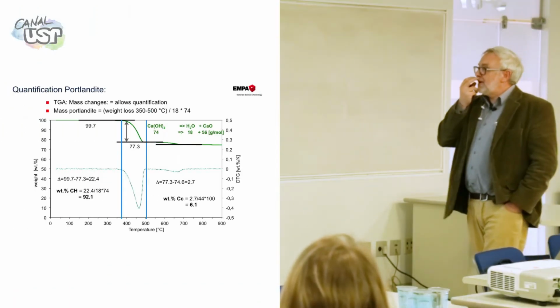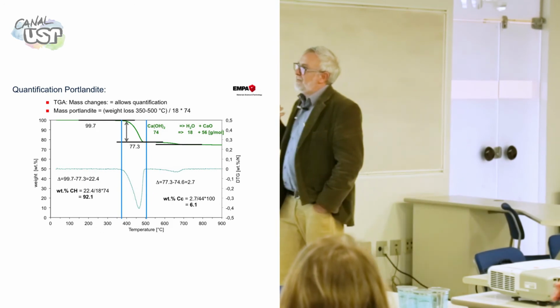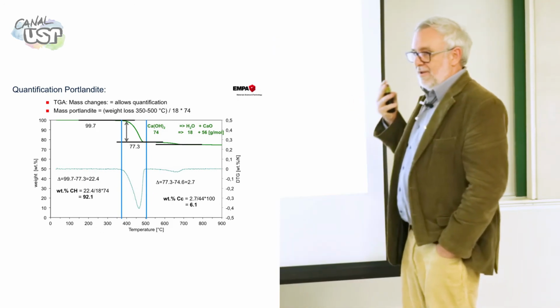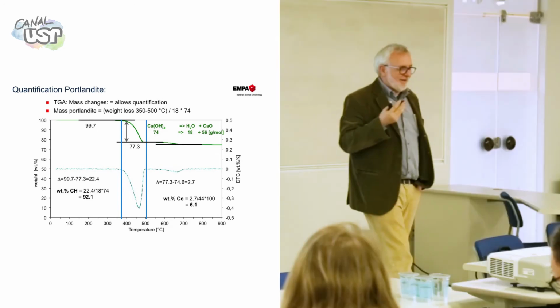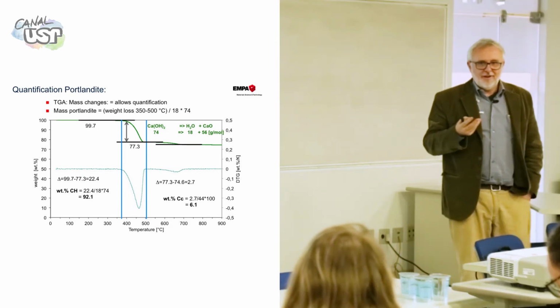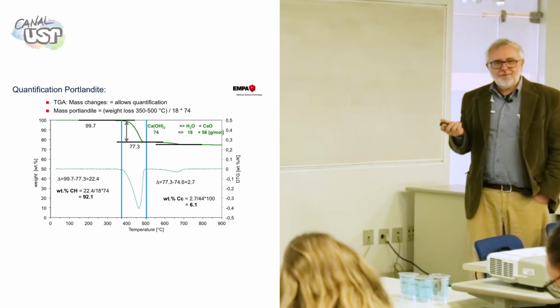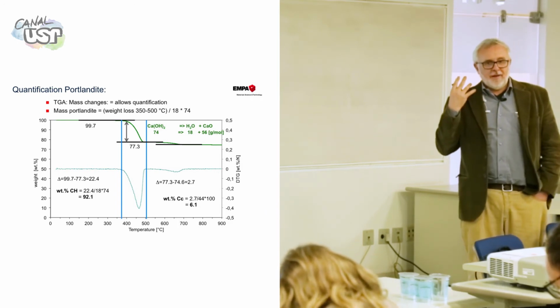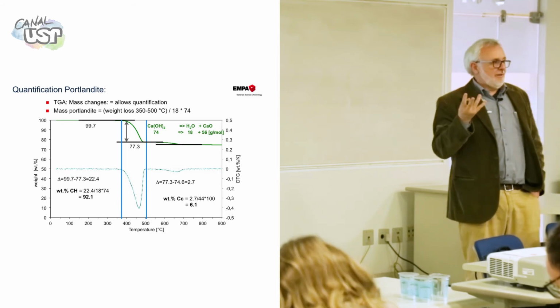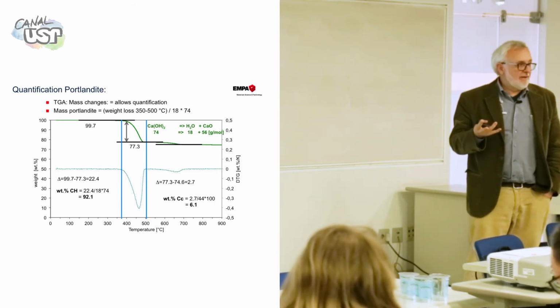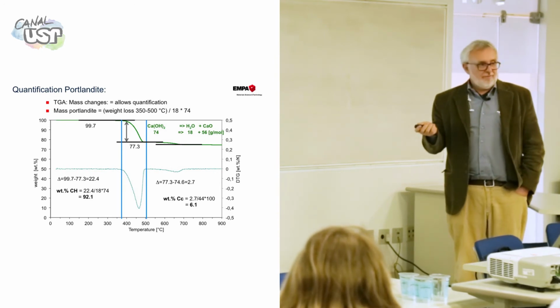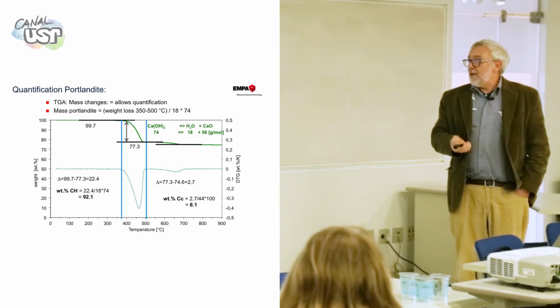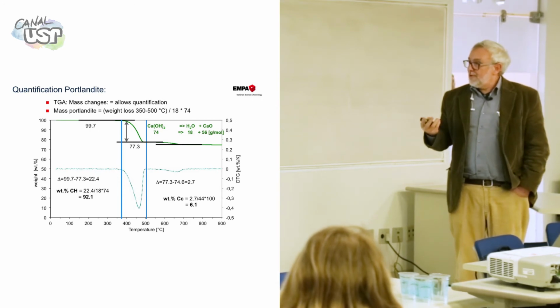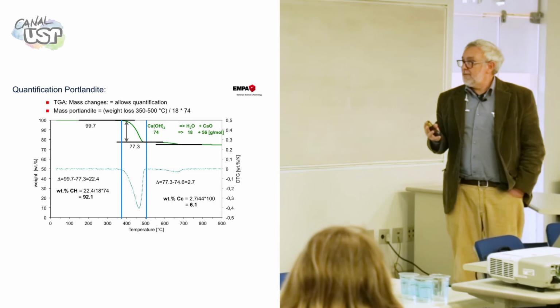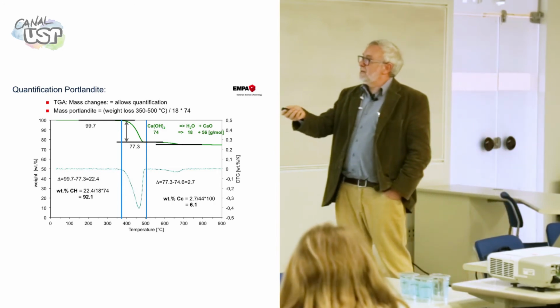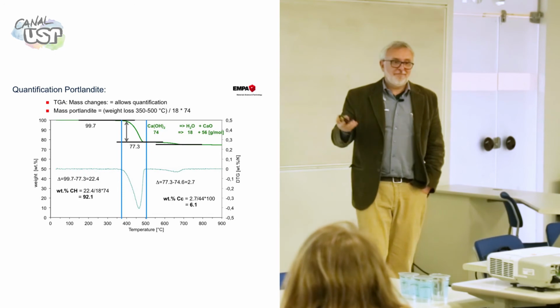I think this is more important, because what you can really measure from TG in a more or less isolated way is the portlandite decomposition. And this can help you to track hydration. You can track pozzolanic reaction very easily because it's going to consume portlandite. You can also have a good glance at carbonation. Okay, so this is very good. And this is what it looks like. You can think of hydrated lime, CH.